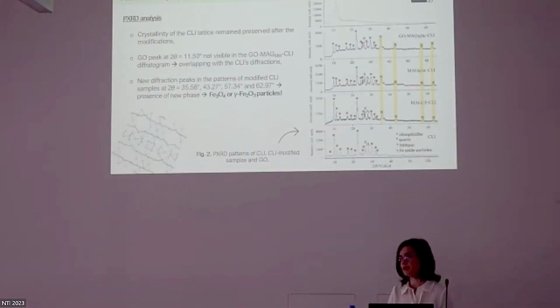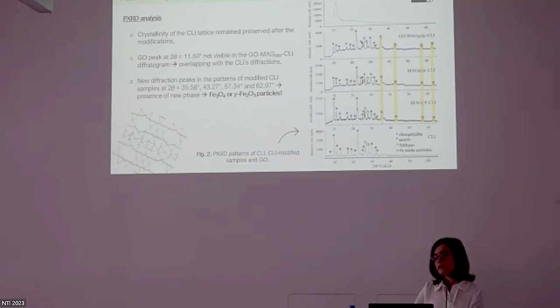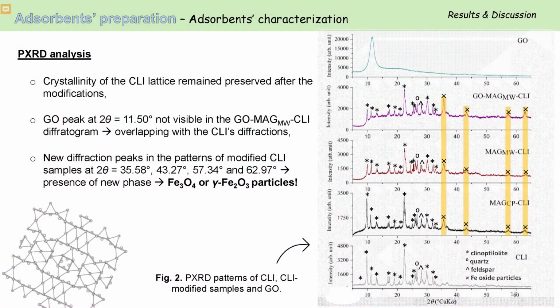So I will continue with the results and discussion, but first I will go through the characterization of the prepared adsorbents. So the PXRD analysis showed that the crystallinity of clinoptilolite remained preserved after the modifications. The characteristic peak of graphene oxide is not visible in the graphene oxide modified samples due to the overlapping with clinoptilolite diffractions. On the other hand, 4 new diffraction peaks are visible in the patterns of samples modified with magnetic nanoparticles, indicating the presence of a new iron oxide phase. This can be attributed to either magnetite or maghemite particles.